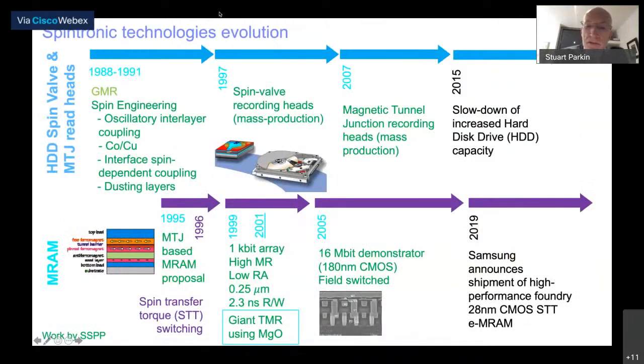I wanted just to then briefly show you how these have evolved over the last 25 years. As I mentioned, on the top you can see the evolution of magnetic disk drives. And I mentioned already that the spin valve device that I introduced was based on novel materials, interface spin-dependent scattering, and in particular the oscillatory interlayer coupling that I discovered, which enabled us to create spin valve devices that were actually useful in magnetic disk drives. And these were introduced in 1997.